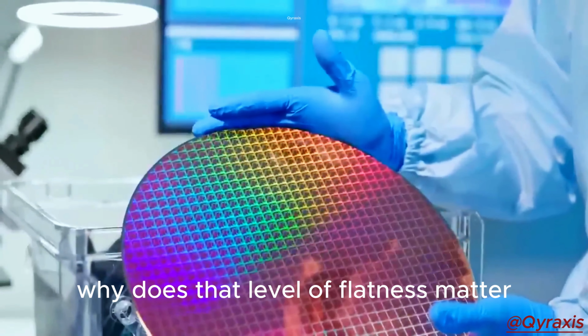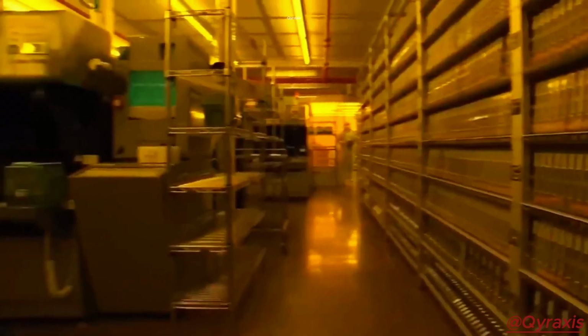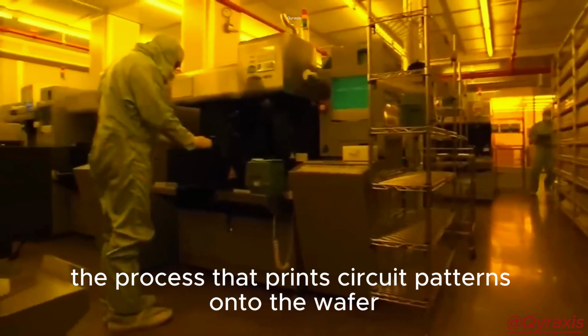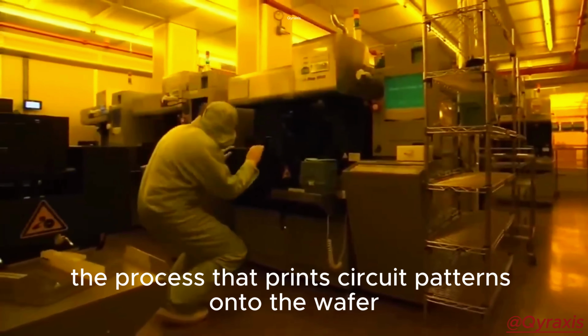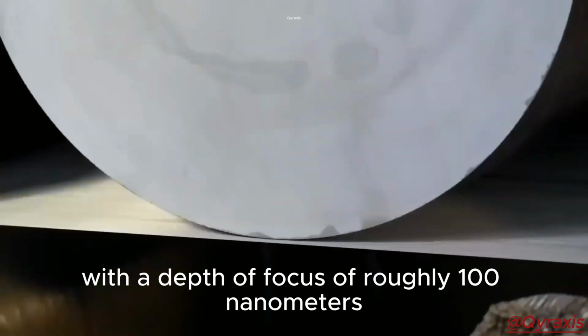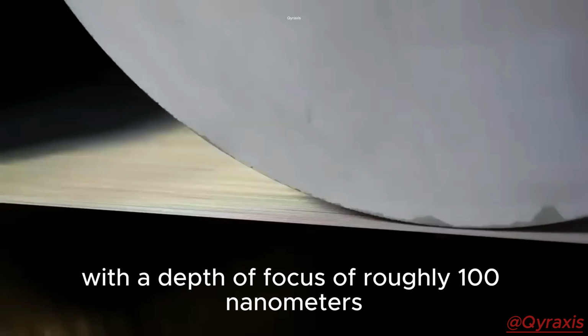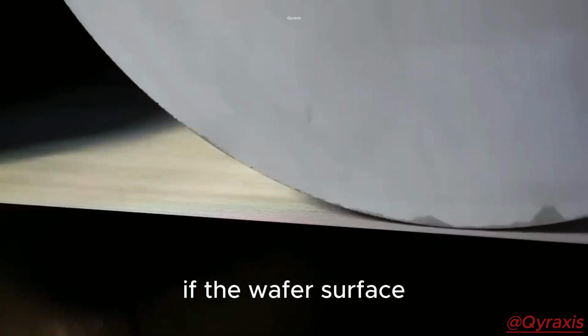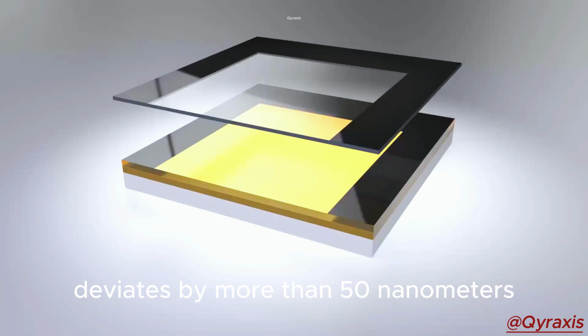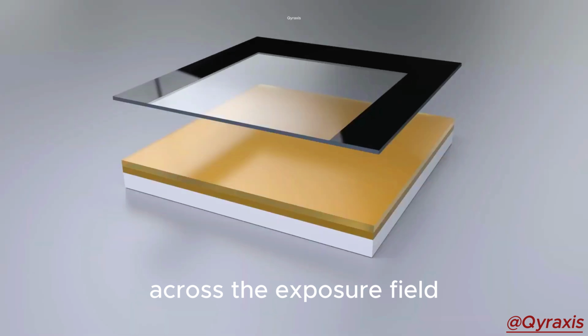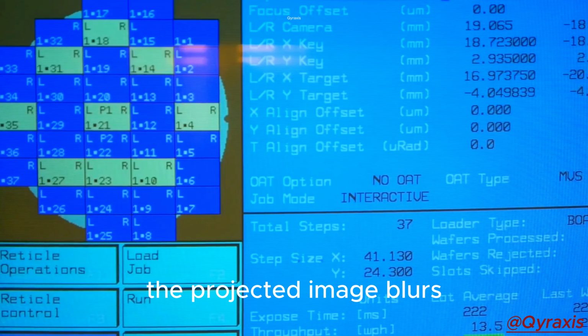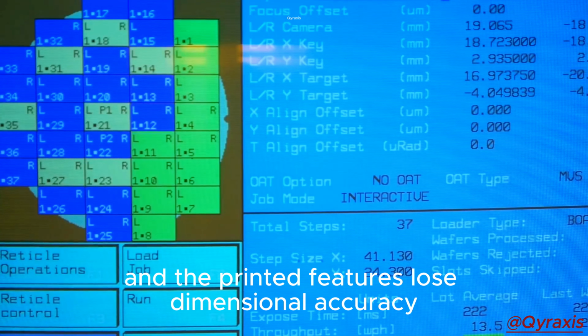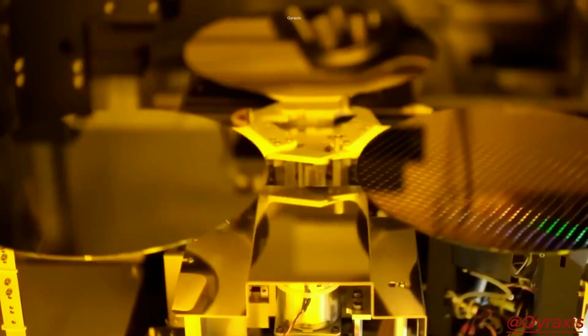Why does that level of flatness matter? Photolithography, the process that prints circuit patterns onto the wafer, operates with a depth of focus of roughly 100 nanometers. If the wafer surface deviates by more than 50 nanometers across the exposure field, the projected image blurs and the printed features lose dimensional accuracy.